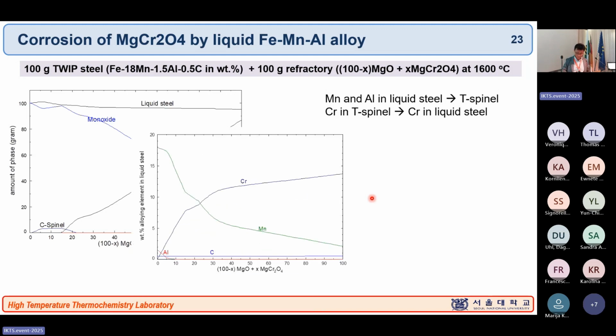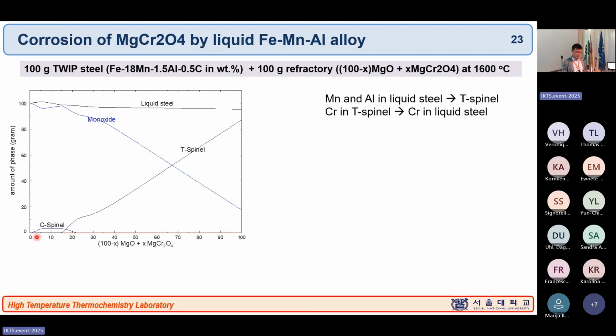And it is not. In fact, if you look here, this is pure MgO, and this is MgCr2O4. I did a thermodynamic calculation, assuming 100 gram of TWIP steel with 100 gram of refractory, but the x-axis here is changing the composition. So here is pure MgO, and here is pure MgCr2O4 at 1600 degrees Celsius, and I plot what kind of phase can be formed. Of course, there's the 100 gram of liquid steel, and you can see that different kinds of phase can be formed depending on your composition thermodynamically.